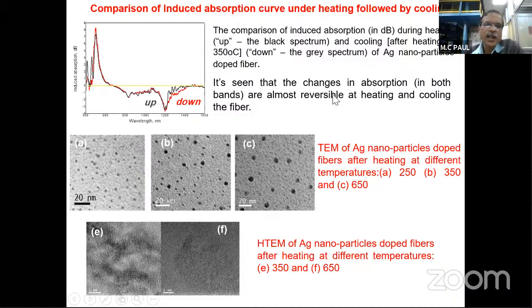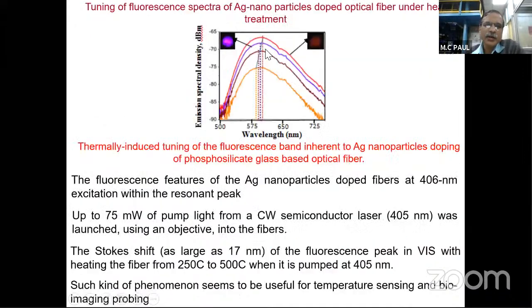And this is the fluorescence spectra we have taken with increasing temperature from 250 to 500, with a gradual shift of the peak, and the wavelength shift is around 17 nanometer. This kind of phenomenon will be useful for temperature sensing and bioimaging fiber. This is the beauty of this nanoparticle fiber we have developed in our lab, basically phosphosilicate glass.